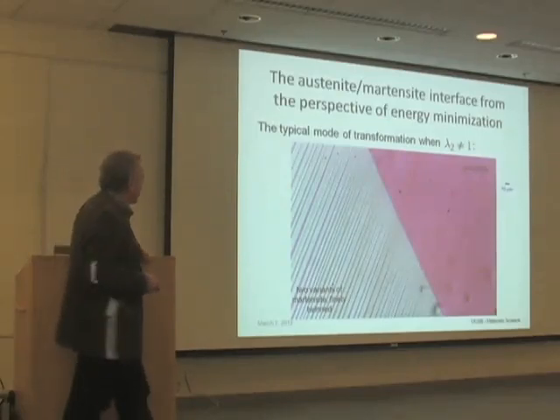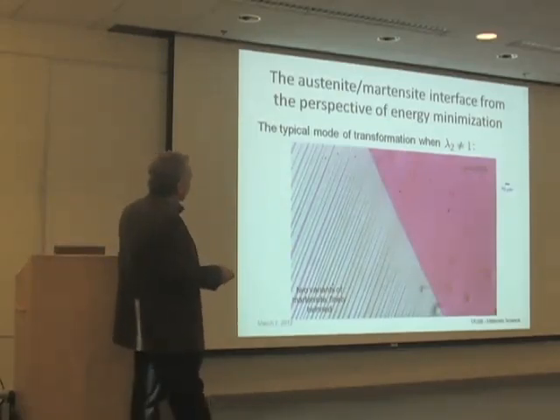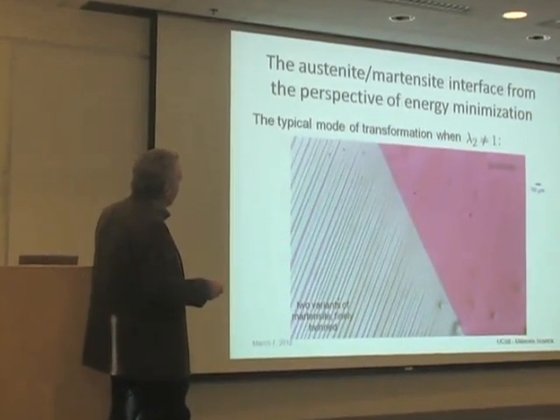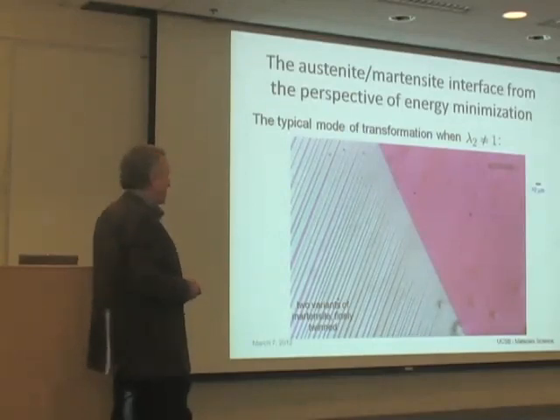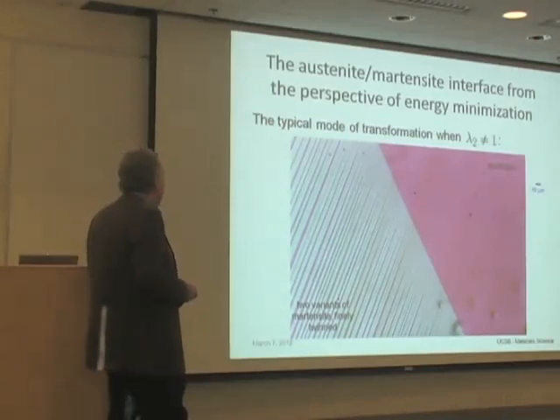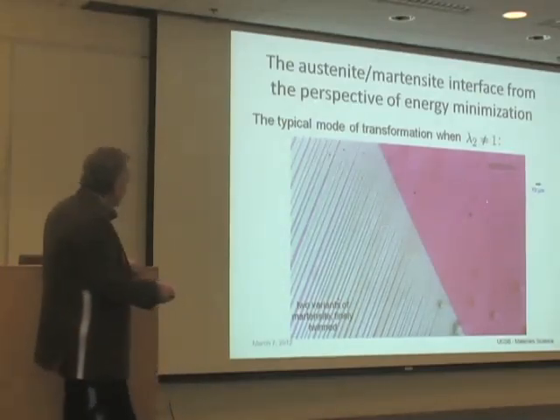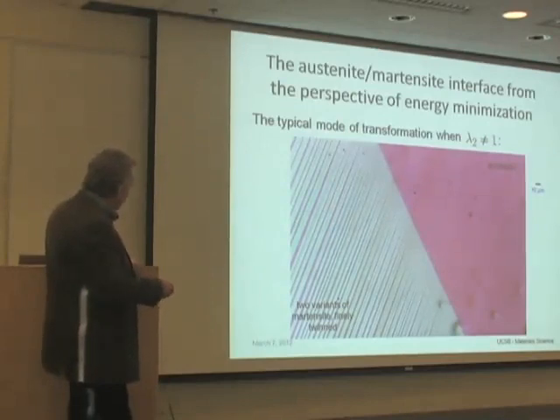And everything I'm going to say for the next few slides occurs when the middle eigenvalue of the transformation stretch matrix is not equal to 1. Okay, and there's the austenite phase. That's a kind of snapshot. It's a different material than the previous picture, but it's qualitatively the same microstructure. It's quantitatively a bit different. So the point is the austenite is not compatible with a single variant of martensite, and again, I'll explain more, but it's compatible with a fine layering of two variants of martensite. This is alternating bands of martensite.